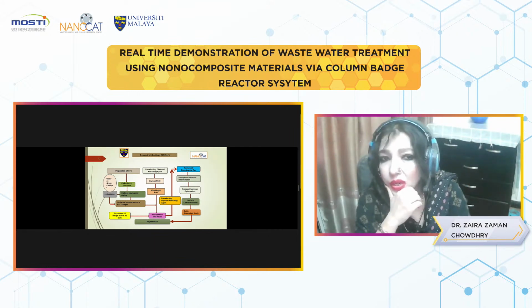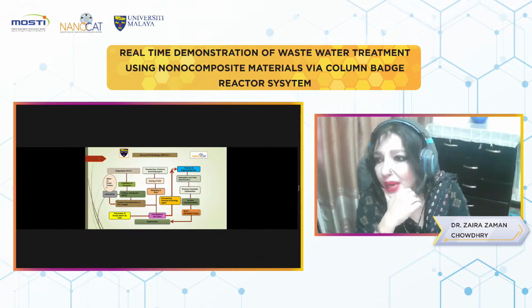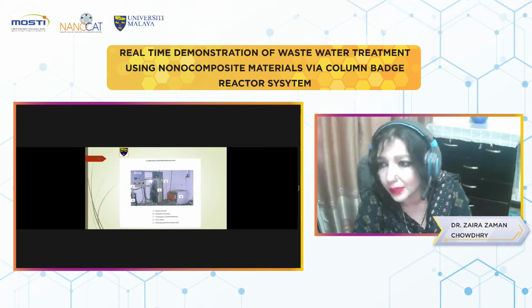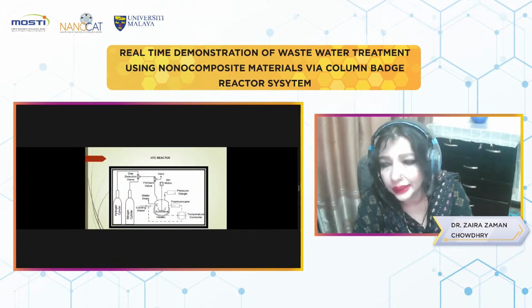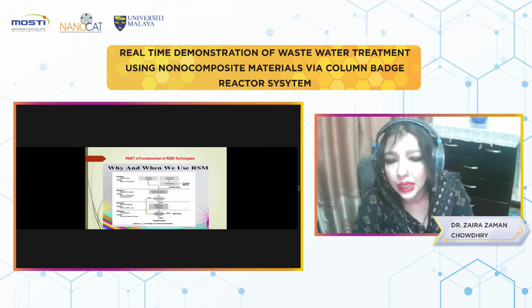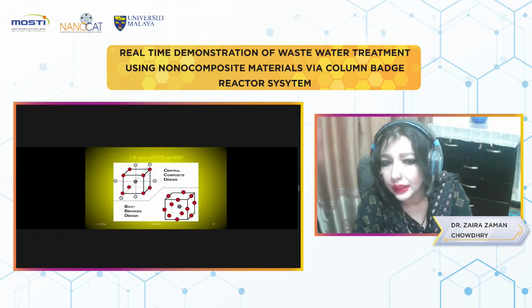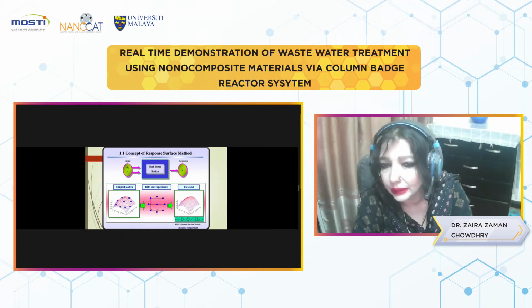So what we have done: we have prepared some hydrochar from cellulosic waste, and then this hydrochar was activated by potassium hydroxide. We have used design of experiments. We have performed 29 experimental runs to check how much copper is removed by each run and how much activated carbon is produced, I mean the yield of the carbon. This is our basic apparatus, pyrolysis apparatus, by which we have prepared our activated carbon. This is a hydrothermal setup. We have used the RSM technique, Box-Behnken design.